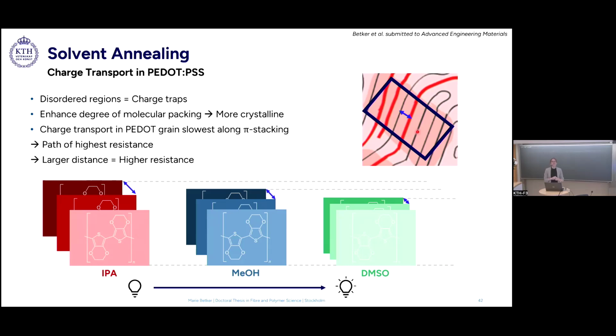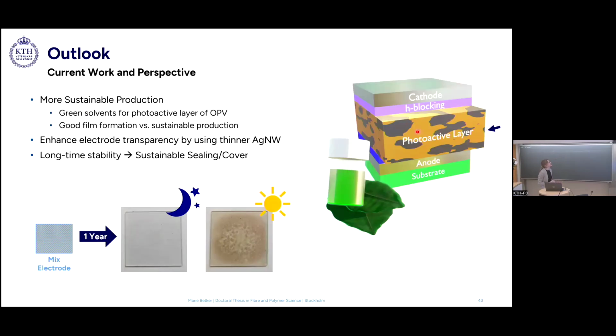So this was a short summary of my PhD thesis with a special focus on conductivity. But of course, there's always room to do more. And so in my 4th manuscript, I focus more on the sustainable production via spray deposition. And it's more focused on the photoactive layer of the solar cell. So here, green solvents instead of the toxic halogenated solvents for the fabrication of the photoactive layer in a solar cell. However, in this project, we found a conflict between a good film formation, which is important for the conductivity in this layer, and the sustainable production, meaning the use of green solvents. So more work needs to be done in this regard.